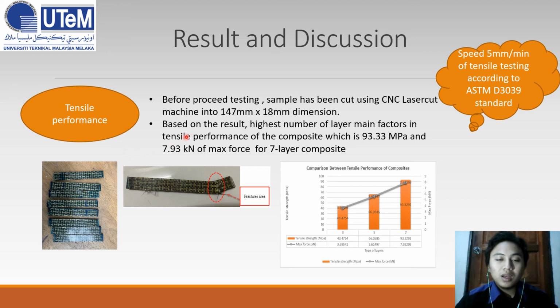Based on the data obtained, the highest number of layers is the main factor in the tensile performance of the composite, which is 93.33 megapascal and 7.93 kilonewton of maximum force for the 7-layer composite. So based on the data, the higher the thickness, the higher the tensile strength obtained.